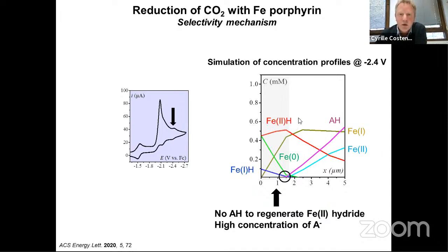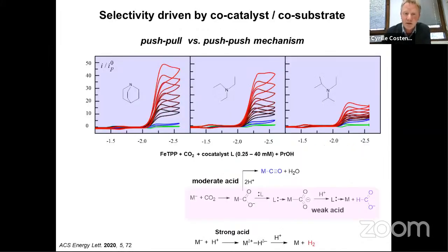If you put CO2, CO2 will react with this hydride. You will get formate and get back to iron 0, but there is no more acid to regenerate the hydride. So it's not possible to get catalysis here because you cannot turn over, because of the absence of acid. Okay, so this means that the mechanism is different, and we have proposed a different mechanism that is also based on the observation of the role of a co-catalyst.